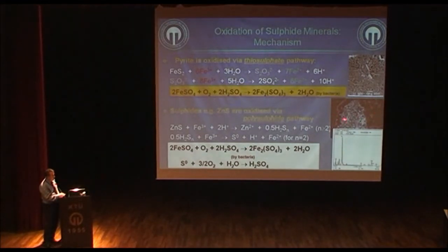We see from here as well, this particular ore particle was subjected to the biooxidation, and we see the accumulation of sulfur on the mineral surface. And if there are sulfur oxidizers within the system, this sulfur will be removed from the surface of the mineral.